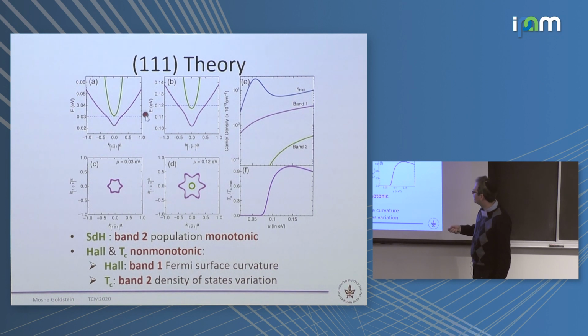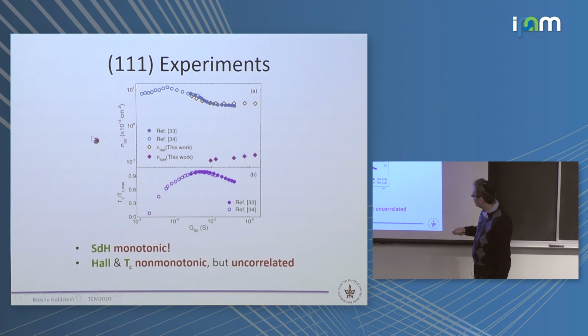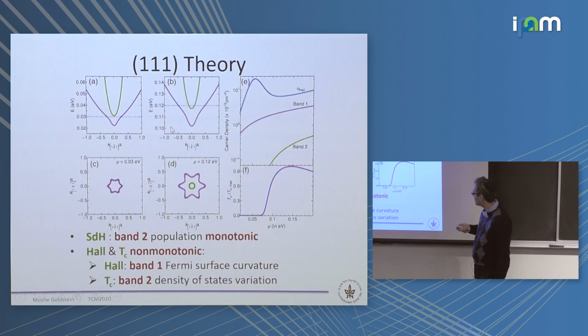And therefore, indeed, when you do the calculation with basically the same parameters as we used for 100, you find that both bands have monotonic population. And this is why Shubnikov-de Haas now is monotonic. It again seems to be probing band number 2, but it's monotonic. So this roughly corresponds to what we have seen in Shubnikov. As for the Hall, we see something which is non-monotonic, but this is actually happening before we start feeling band 2, right? This peak is happening before we start feeling band 2 and seeing things in Shubnikov.